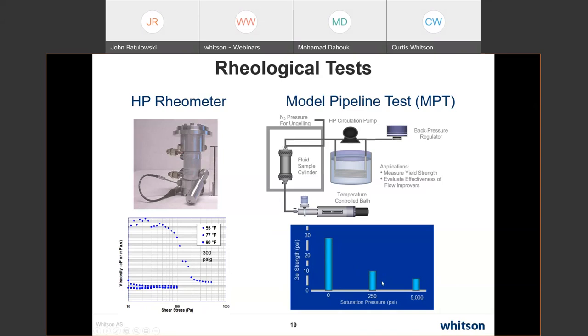So you would expect in a live oil system that your actual gel strength and your pour points are going to be somewhat reduced over those measured on dead oil. But a lot of people use the dead oil results just to be conservative, but you do have a lot of leeway there.